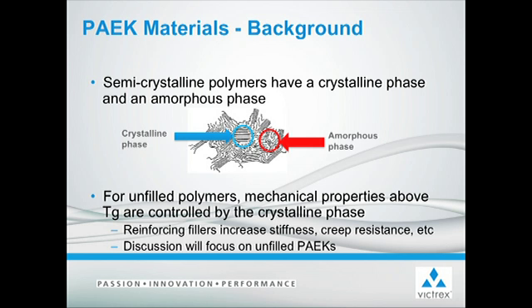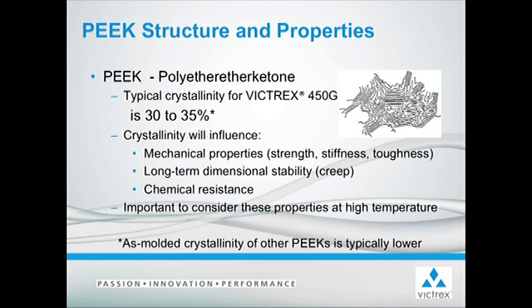The crystalline regions within a semi-crystalline polymer act to enhance their mechanical properties, just like you see with the addition of reinforcing fillers like glass or carbon fibers that help to increase strength and stiffness. If we take VICTREX PEEK 450G as an example, it contains 30 to 35% crystalline material within its structure, which is higher than most other PEEKs available on the market.